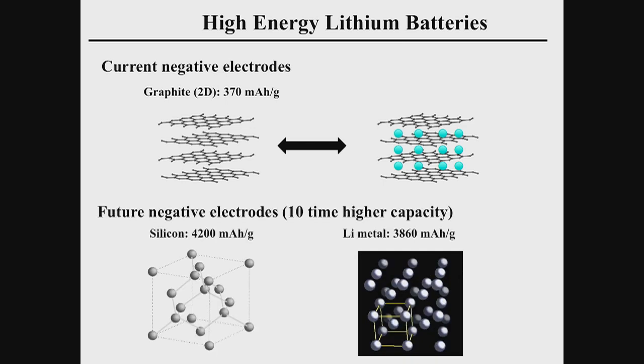And what's the choice beyond graphite? If you look at a new material, silicon. Sitting in Silicon Valley right here, every time I see silicon, I get excited, because the whole valley knows so much about it. Silicon can actually store a lot more. Lithium comes in through a different mechanism from graphite: it cleaves the silicon-silicon bonds and forms lithium-silicon bonds. This number compared to that number is 11 times.